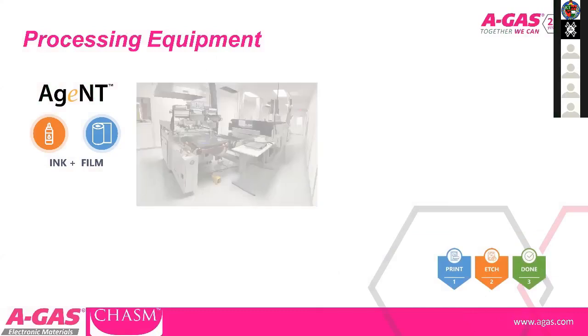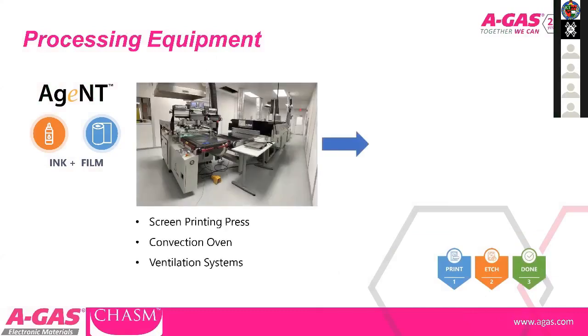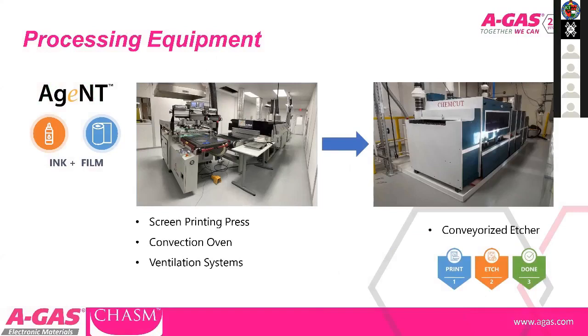The process essentially follows two simple steps: a screen printing process with a quick dry, and then a very mild etch-rinse process. This is a far simpler route than ITO, which involves laser ablation processes for patterning. And because this involves screen printing and a mild etch process, these are technologies that a lot of PCB manufacturers and printed electronics manufacturers already have in-house.